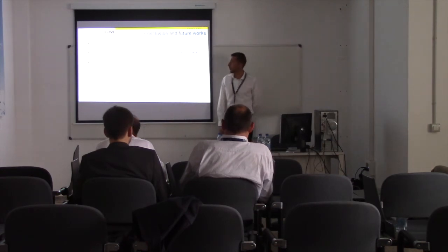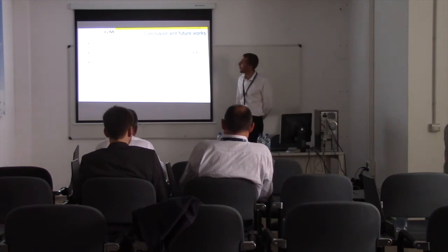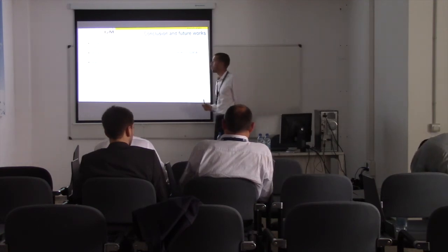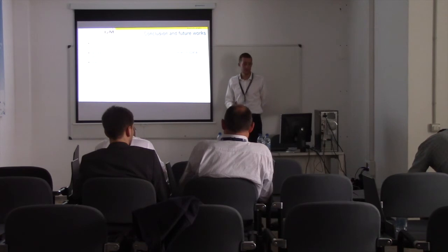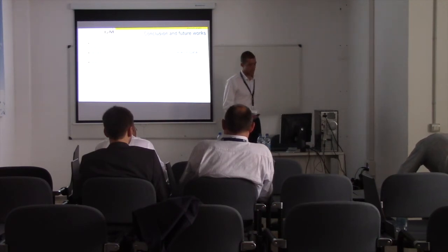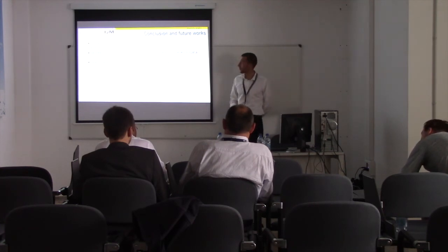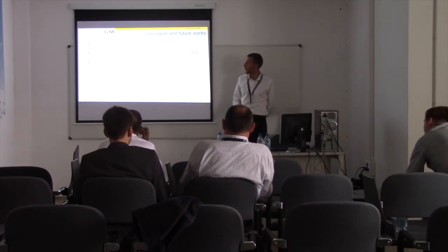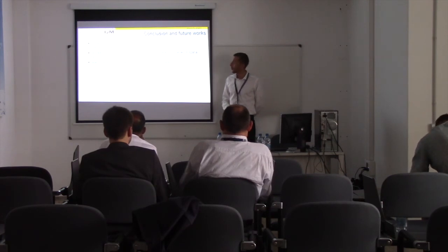So to conclude, powder size distribution affects the packing density due to particle arrangement mechanisms. We now want to be more qualitative to help our manufacturer. Recoater type and speed need to be optimized to have a homogeneous spatial distribution, and the layer thickness and layer properties vary with the previous layer.